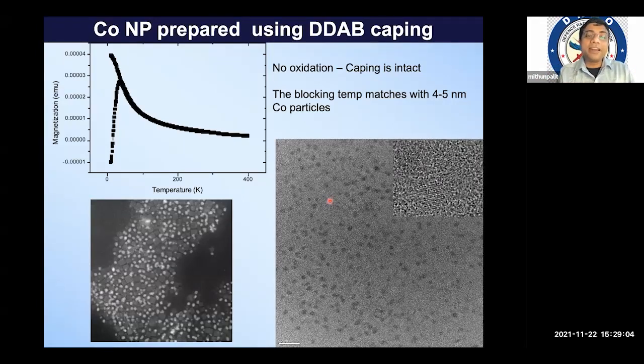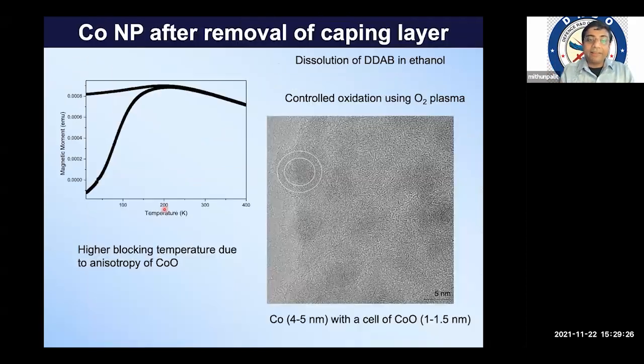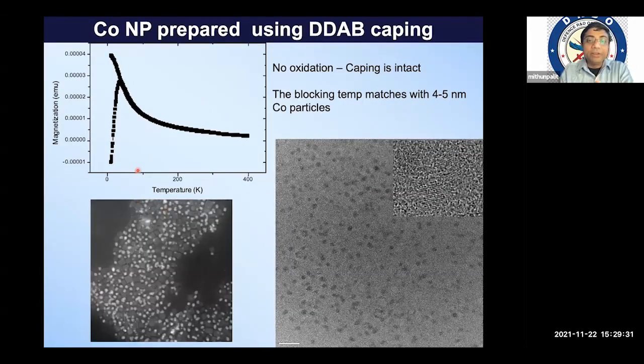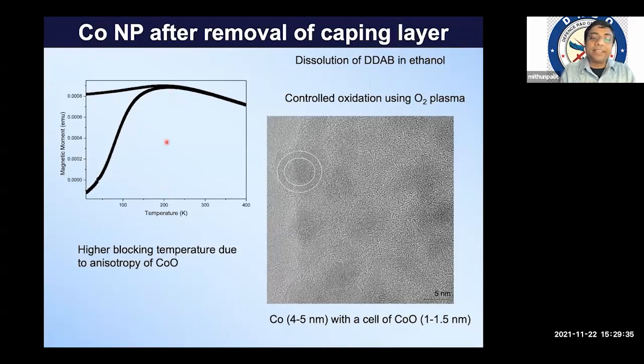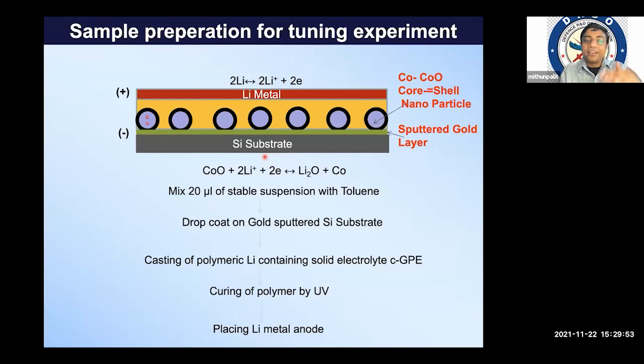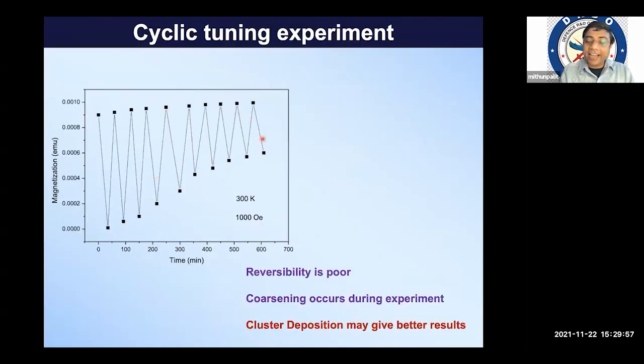The other concept is the cobalt nanoparticle. Normally this cobalt nanoparticle shows blocking behavior. You can see this is the blocking behavior. It shows a blocking temperature around 50 Kelvin. But if you produce some cobalt oxide, that is, you oxidize the cobalt on the surface to form a cobalt oxide shell, then the blocking temperature, which was at 50 K, due to this antiferromagnetic cobalt oxide, comes to almost close to room temperature. You see the high resolution transmission micrograph, where you can see two layers: the core, which is the cobalt nanoparticle, and cobalt oxide in the shell. So we devised a system and carried out the tuning experiment. However, here the reversibility is not as good as what we achieved in the earlier system. However, some more work can be done to optimize this cobalt oxide formation and the reduction.